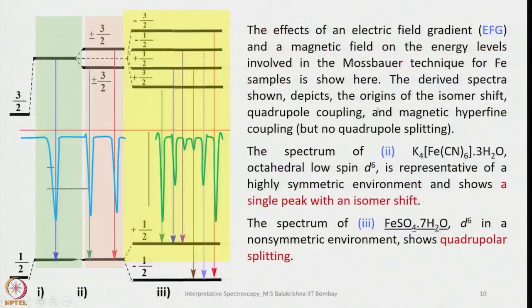And then we get the spectrum. Then the effect of an electric field gradient, which is abbreviated as EFG. Later, if I say EFG, it should be understood as electric field gradient. The effect of an electric field gradient and a magnetic field on the energy levels involved in the Mössbauer technique for an iron sample is shown here. The derived spectra depict the origin of the isomer shift, quadrupole coupling and magnetic hyperfine coupling, but no quadrupole splitting.